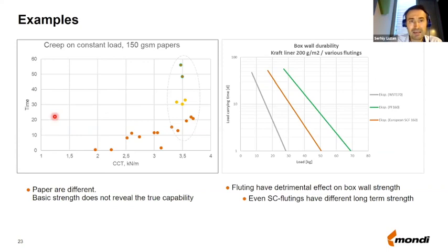What is important to say and underline once again is that the static tests quite often don't show you the difference between the papers so well, as they do not so closely reflect the real life conditions. So on this graph, you see a comparison for different papers, all papers taken in 150 GSM. On the X axis, you have the CCT values of these papers, which is a static test. And on the Y axis, you have the time in days showing you how long this paper will hold the load in the creep test. And you see that especially for strong papers here, you have quite similar performance when it comes to CCT, but very different performance when it comes to creep.